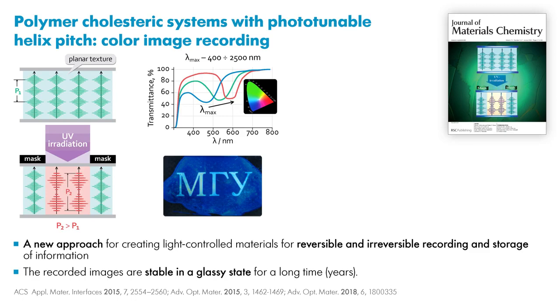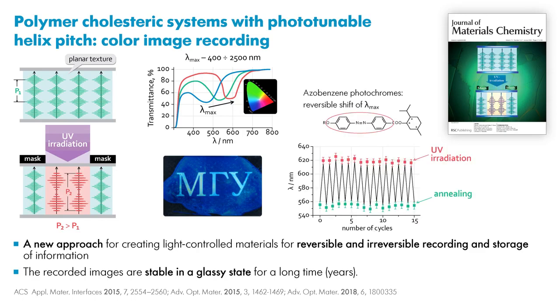Here is an example of a color image shown, yellow letters on a blue background. In the case of benzylidene menthanone, photoisomerization is irreversible. However, for the azobenzene derivatives, we have realized cycles of selective light reflection shift during sequential UV irradiation and annealing. In summary, we have developed a new approach for creating light-controllable materials for reversible and irreversible recording and storage of information. Note that the recorded image is stable in the glassy state for a long time, for years.